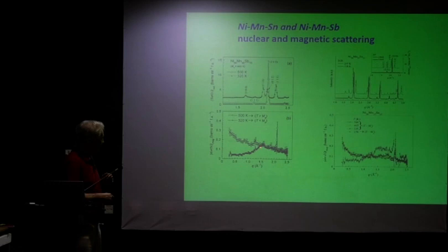And in addition to that, when you have seen this drop, you can say that this thing that you have in the back, which is also a magnetic scattering, is related to some antiferromagnetic correlations. But here, the ferromagnetic correlations dominate. So at high temperatures, you have the ferromagnetic correlations and the antiferromagnetic correlations. And when you go to low temperatures, you're left with the antiferromagnetic correlations.